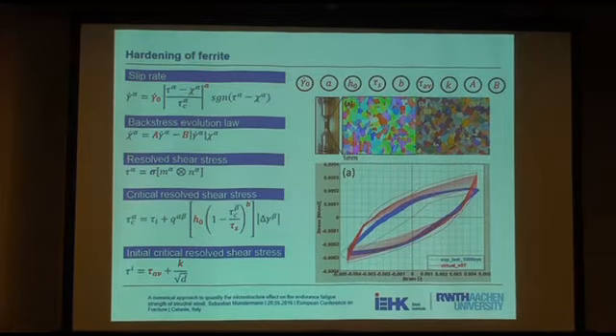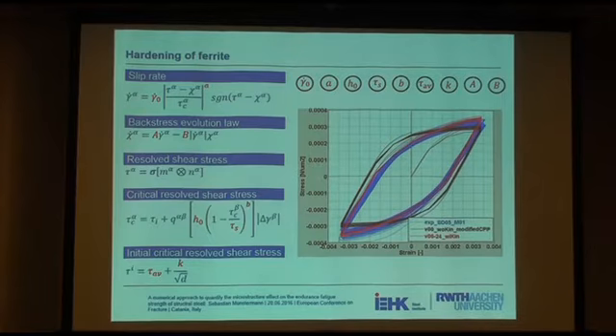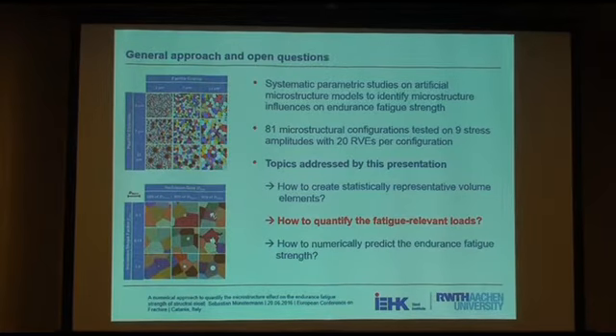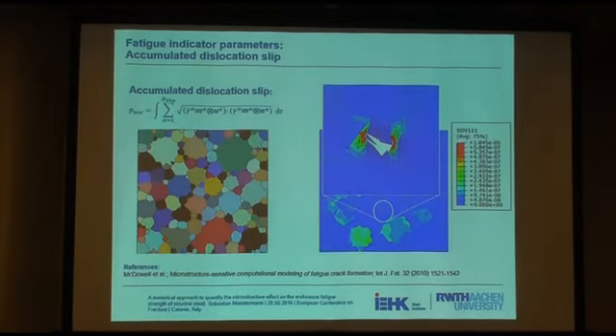Here you can then see some experimental results that were achieved in stress-strain experiments. You see how we calibrated the kinematic hardening parameters, and here you see in red the contribution of both kinematic and isotropic hardening. You see good agreement with the experimental results, so we believe that this is expressing the reality quite well.